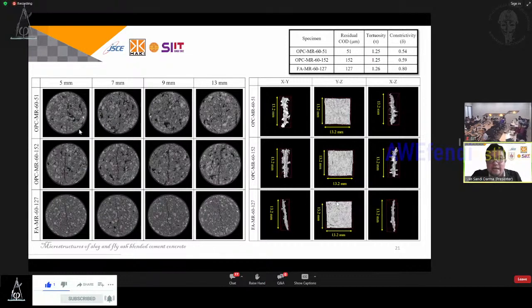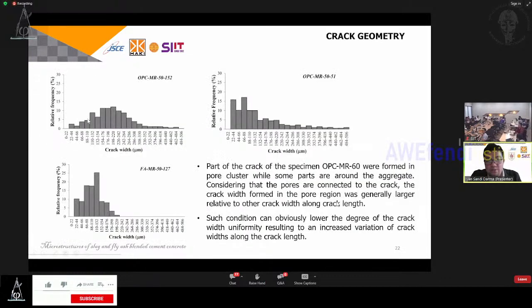And then this is the crack width distribution. We also calculate the crack width distribution using images, especially for both. As you can see here, for OPC, the distribution of crack width is quite wide compared to the fly ash. It ranges from 0 to 484 for the OPC, and for the fly ash, from 0 to only 200.